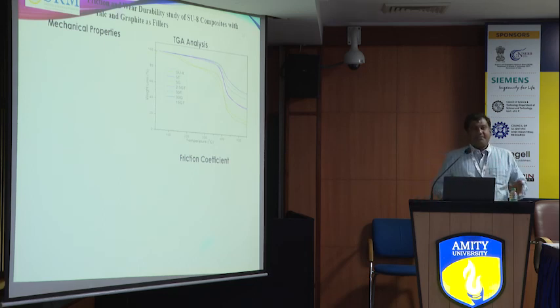So very good bonding happens because of the OH group present in the talc. I also found that it is very good for this research, and without adding any lubricant, the friction of SU8 has a coefficient of friction of 0.6 to 0.7. By adding this graphite and talc, we reduced it to 0.2.